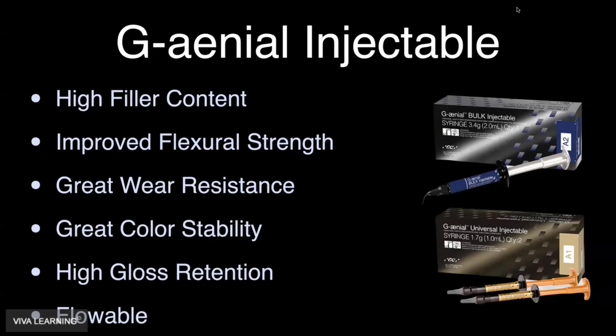Which is why really we're going to call it an injectable composite, okay? Because it is a standalone restorative material. You can use this material for the functional surfaces, so occlusal surfaces in a class 1 or class 2, lingual surfaces in a class 3 or a class 4. You do not have to put anything else into the cavity preparation other than this material. And that's true because it has an equally high filler percentage as all of the composite materials you're accustomed to using, that you have to put a little compule in a composite gun, or that come in a syringe and you deliver to the cavity preparation on the end of a plastic instrument.